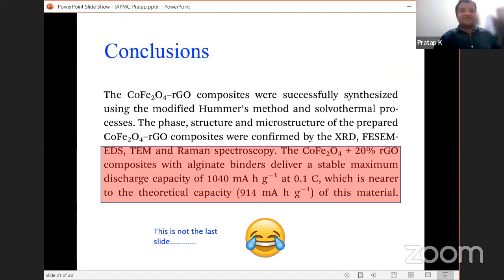And so we made the cobalt ferrite, successfully synthesized it using solvothermal, and characterized it with XRD and FESEM. The discharge capacity is 1040 milliamp hour per gram at 0.1 C, meaning current rate. So actually we have surpassed the theoretical capacity because we have a binder. Now, of course, this is not the last slide. I'll give 5 to 10 minutes